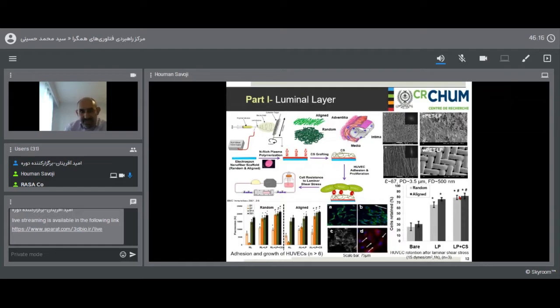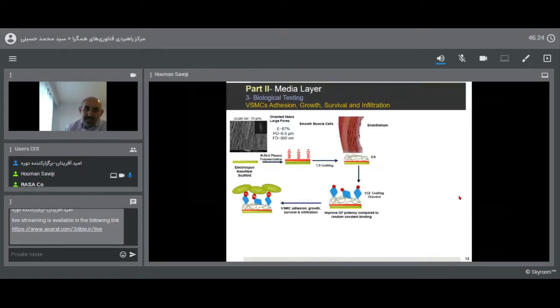So this project was mimicking the first layer, or luminal layer, of the vascular graft, and then we moved forward to develop the second layer, which is the medial layer, containing circumferentially aligned fibers. So we really needed aligned fibers, and we were able to successfully develop these fibers with 87% porosity, a pore diameter of 6.5 micron, and an average fiber diameter of 900 nanometers.